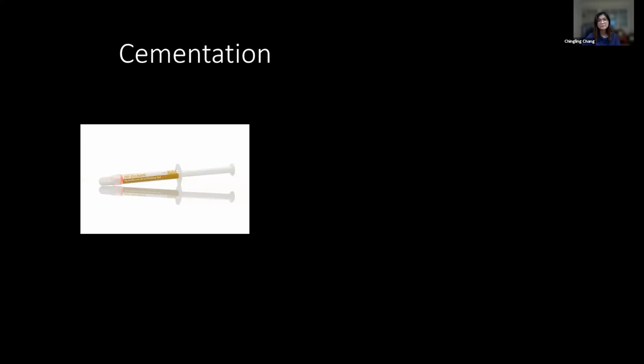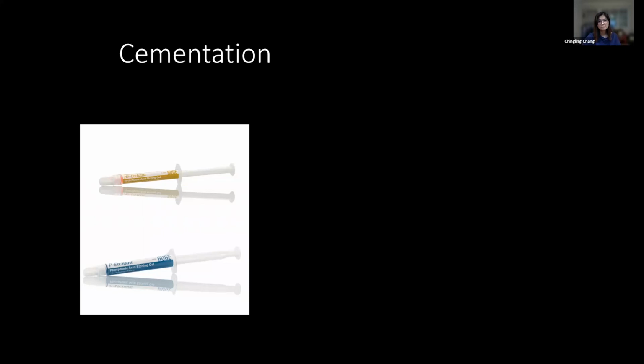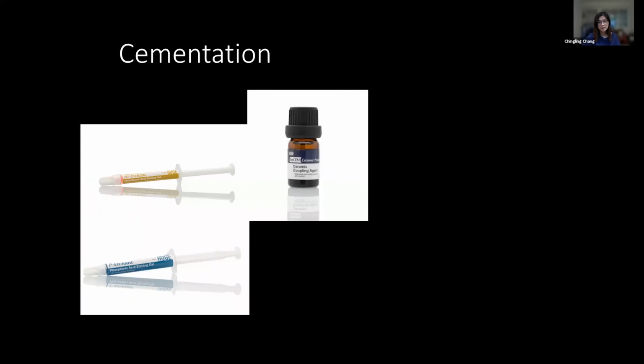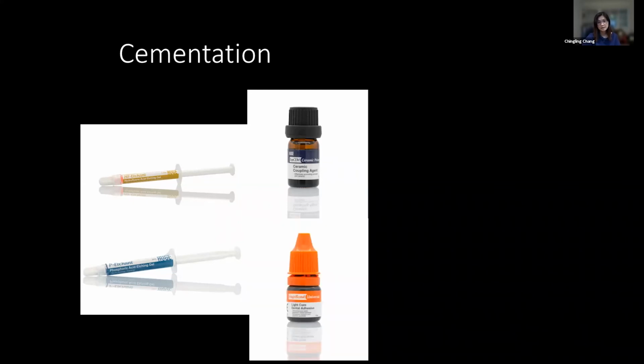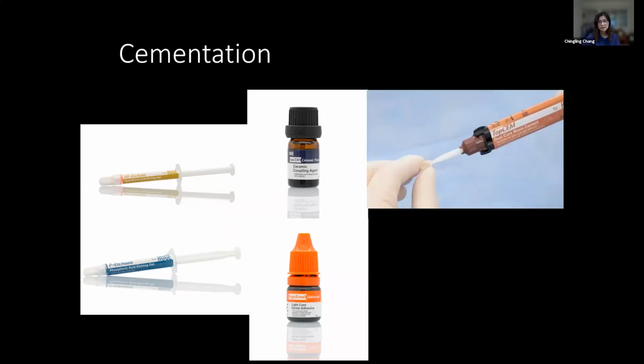Cementation is a very complicated procedure and also involves a lot of material. We use hydrofluoric acid for porcelain. We need phosphoric acid for enamel. And we need a ceramic coupling agent, which is silane, to increase the chemical bonding between the porcelain and the resin. And we use the bonding agent, of course.